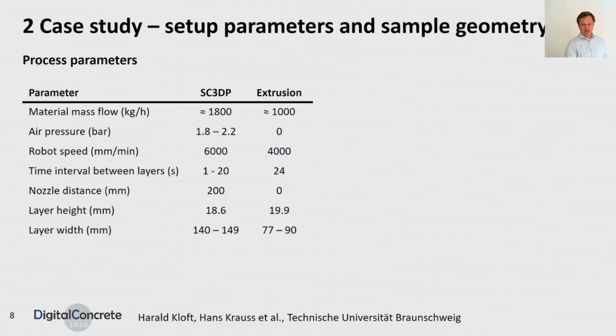The goal was to achieve comparable layer heights, which we indeed roughly achieved. We got about 18.6 millimeters in the case of spraying and 19.9 millimeters in the case of extrusion. And finally, due to the different process characteristics, we have different layer widths of about 145 millimeters, and 80 to 90 millimeters respectively in the case of extrusion.